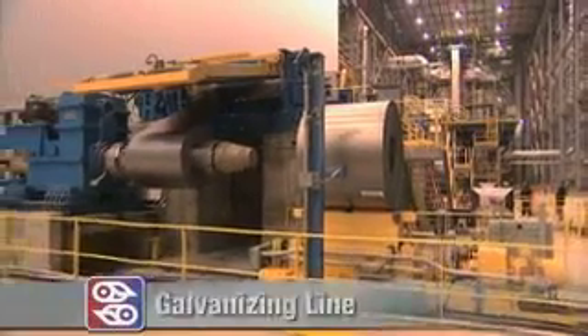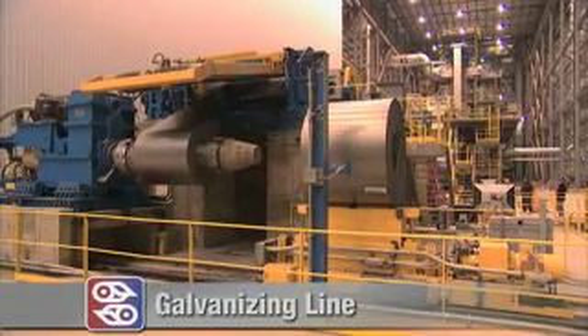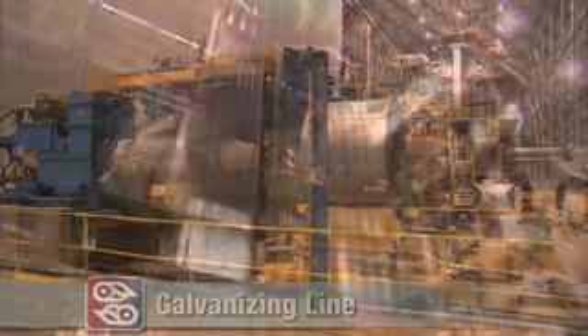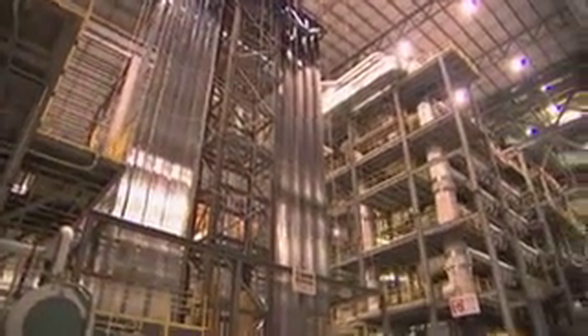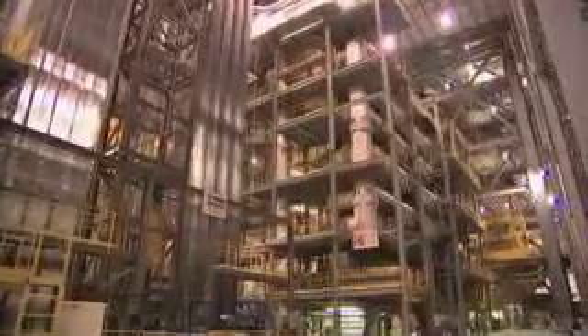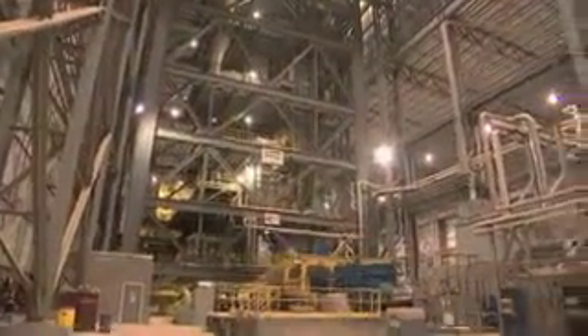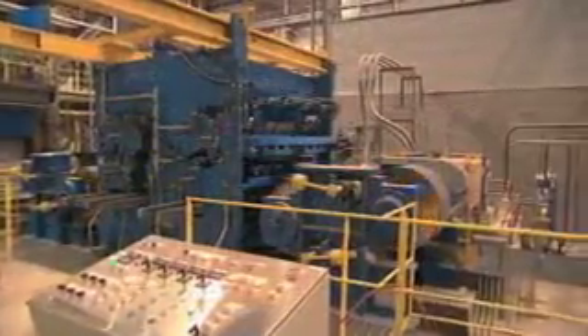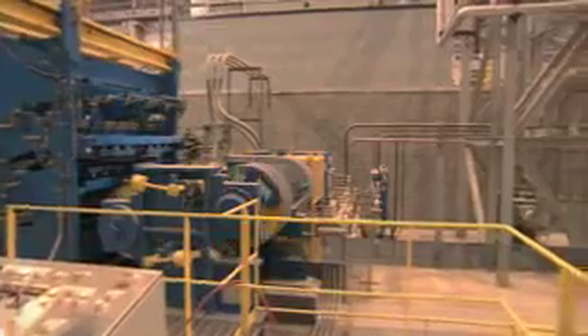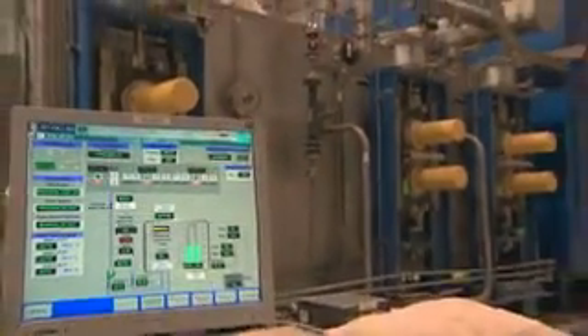For a greater degree of corrosion resistance, full hard cold roll may have a coating of zinc applied at the continuous galvanizing line. The full hard coil passes through a cleaning section, vertical annealing furnaces, and a molten zinc pot. Vertical ovens bake the zinc to the coil. Inline tempering and tension leveling ensure the best surface and shape. Rust inhibitors can be added at this stage if the product will not be painted.